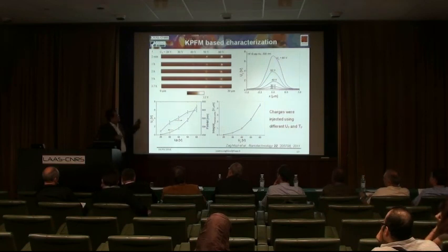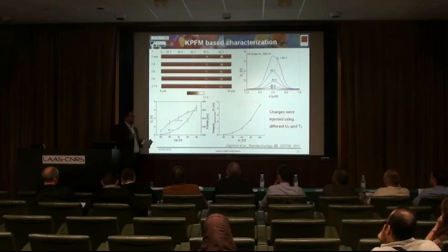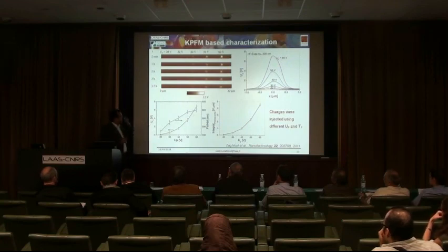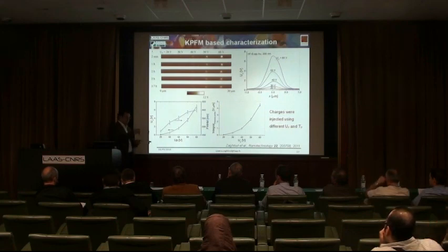The other important issue is that here, we don't measure exactly what we inject, we measure an average. And this is a very big limitation with Kelvin force microscopy, which is solved by FDC. You might ask, so why you injected the charge in points if it has all of these limitations? Because the issue here is, when you inject in point actually, suppose that the surface potential at this point exactly is like 20 volt. Kelvin force microscopy cannot measure this.